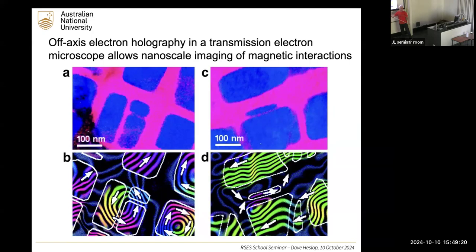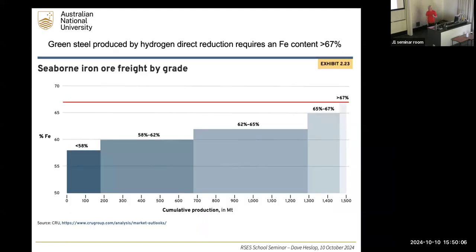So we now have what we call particle-particle interactions, where the influence of the field of the particles plays a role as well. There's an example on the right-hand side here where we've got these two large magnetite particles magnetized in this direction. So this small particle here is minimizing its energy by actually being magnetized in the opposite direction. Now, I don't have any answers at the moment in terms of how to solve these problems in magnetic separators, but this is something I'm going to be working on. And separator design and configuration needs to be informed by these rock magnetic aspects in order to optimize that function.